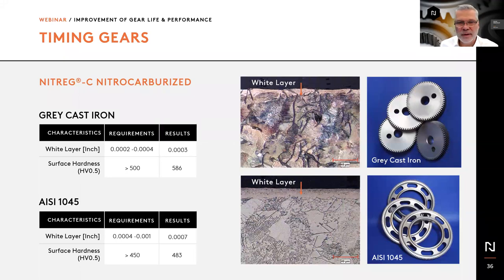And this first example is somewhat strange because the reason for choosing nitriding is the tribology, the type of surface we produce for a quieter gear, for something that will perform with a very, very low coefficient of friction and without any distortion. So typically you use cast iron, but it's soft. Both materials are soft at core, but nitriding produces a white layer, and in both cases improves lubrication, reduces completely wear within at least the warranty covering the vehicle, and it provides for a very, very quiet gear. Next.